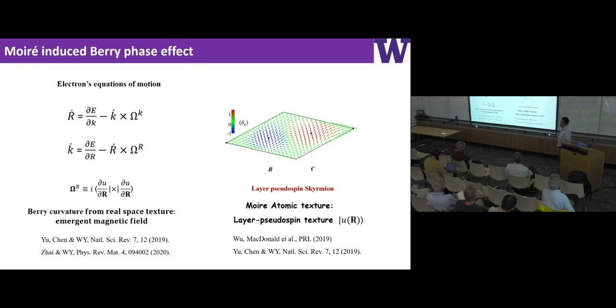But then the situation changes in these moiré sublattices. Let me walk you through it. I told you we have 2 moiré sublattices, B and C, which are energy degenerate. B is with metal on top of chalcogen. C is chalcogen on top of metal. Then you can imagine if I move the position from B to C, this local atomic registry must change. Then this forms these moiré atomic textures. You can basically consider these as layer pseudospin textures. And in Allan's paper, it shows that these are layer pseudospin skyrmions. So we know if there's a skyrmion in real space, then you have this real-space Berry curvature, which gives rise to an emergent magnetic field. So this is the origin of topology in these homobilayer systems.